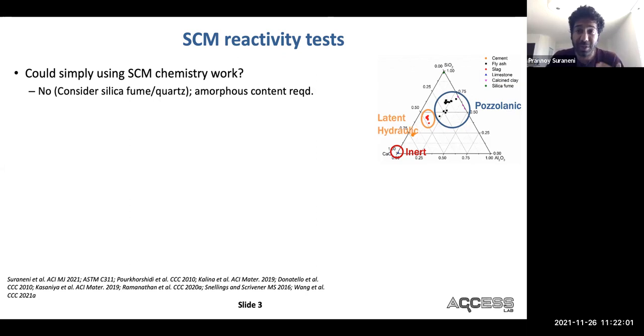It is the amorphous phases that are typically reactive in supplementary cementitious materials, which is why only using SCM chemistry will not work. There are some trends that you can see if you plot a ternary diagram based on chemistry and reactivity, but really these are very approximate, and you want to use them with extreme caution.